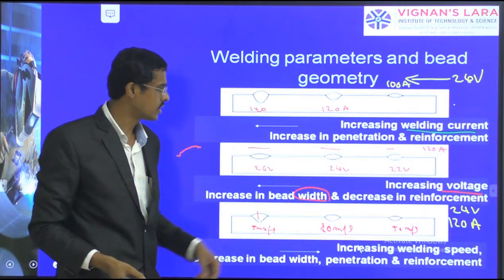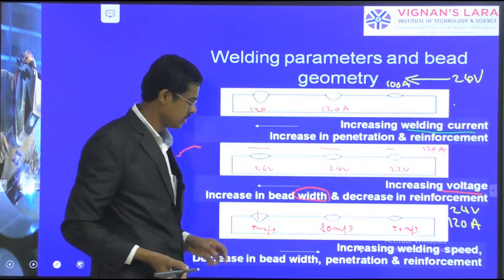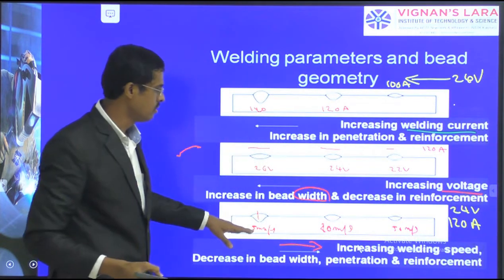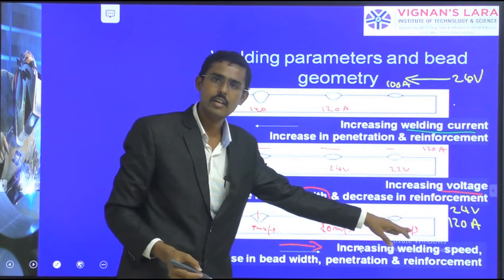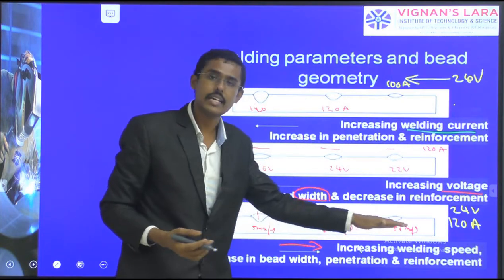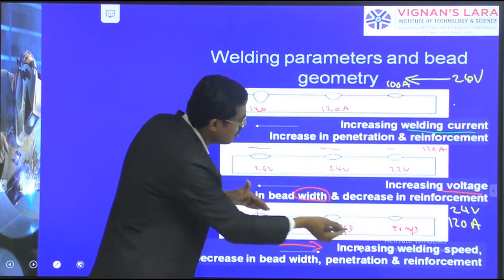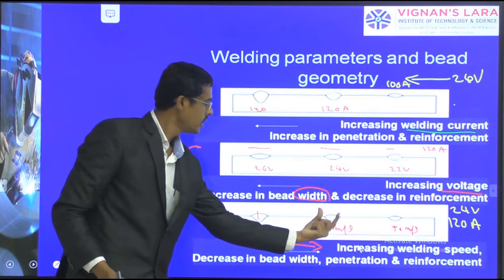Increasing the weld speed decreases the bead width. See, increasing the speed 5, 20, 50 mm per second, automatically the penetration also decreases. The width also. Here the width is this one. Here it is reduced. Here it is much more reduced.